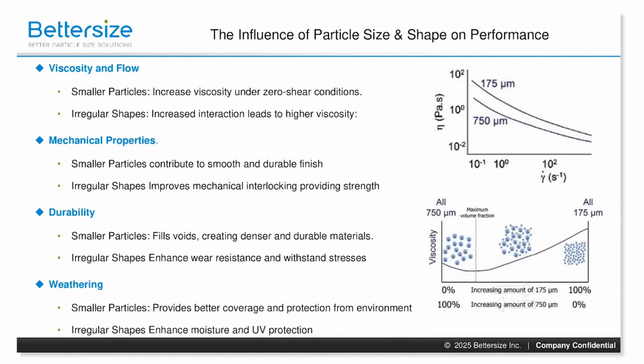Particle size and shape impact other characteristics of these materials. There's viscosity, where smaller particles, with their higher surface area, increase the viscosity of the formulation, which affects the ease of application and leveling. However, irregular shapes can increase interactions with the surrounding fluid, and this can also lead to higher viscosity.